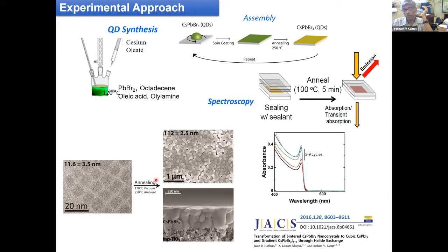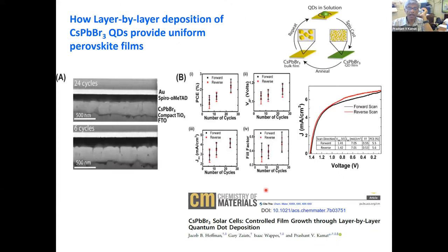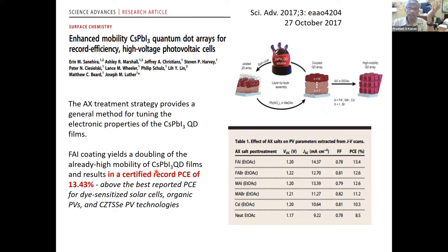And we have followed this growth process and other things. But this is what we use, and we could make solar cells. Again, the efficiency is not something to brag about. It is only 5%, but we showed that it is important to fill in these void spaces by using multiple layers of low concentrations. But people have now reported up to about 13% efficiency for these kind of solar cells. And I think it is still around 13-14%.